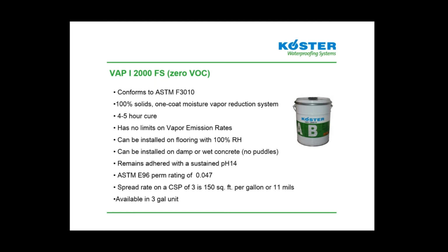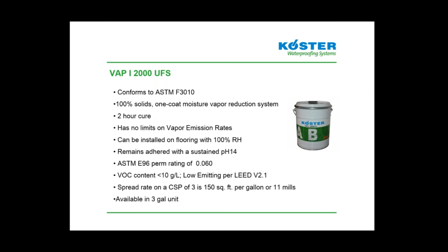This has about a 4-hour cure time with no limits on MVER or relative humidity. This can be installed on damp concrete, wet concrete, or SSD concrete, obviously with no puddles or standing water. Spread rate is the same as all the other products, at least 11 mils.